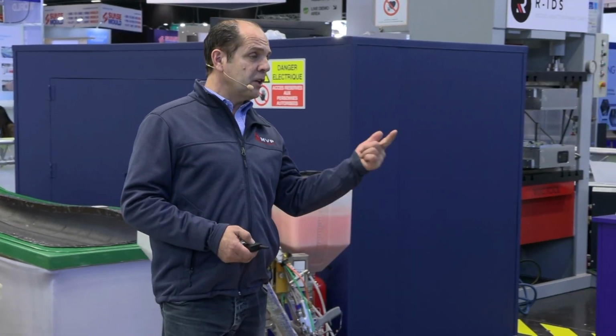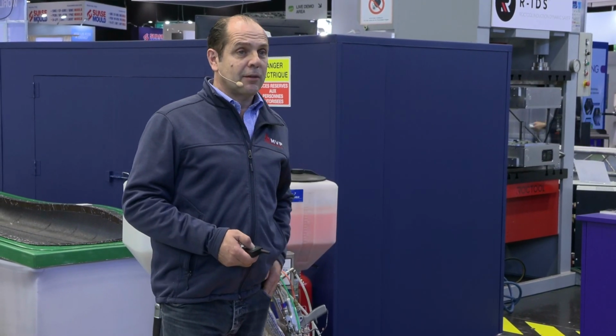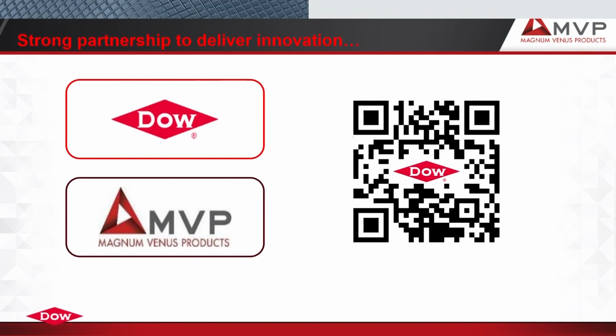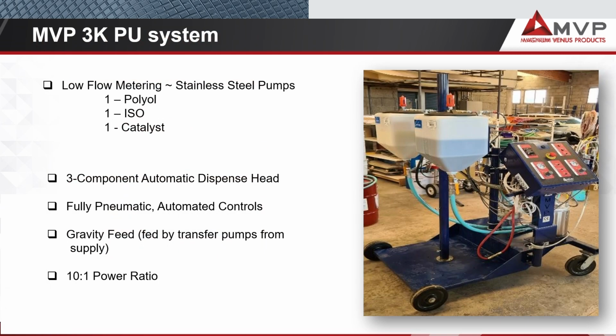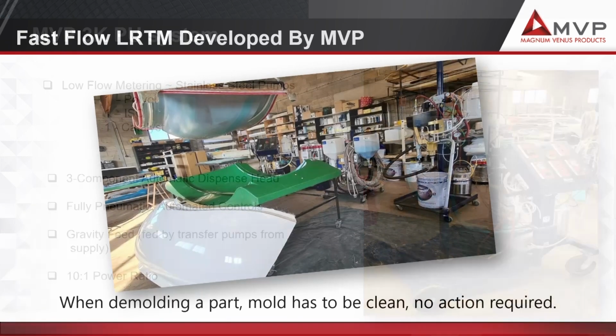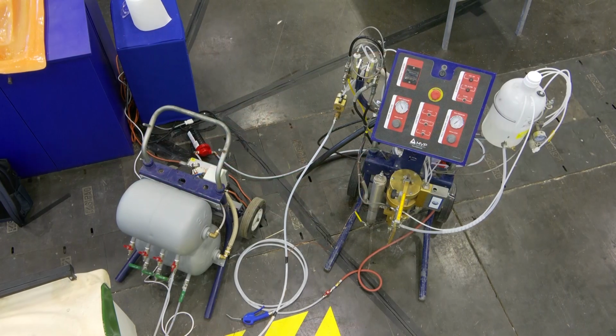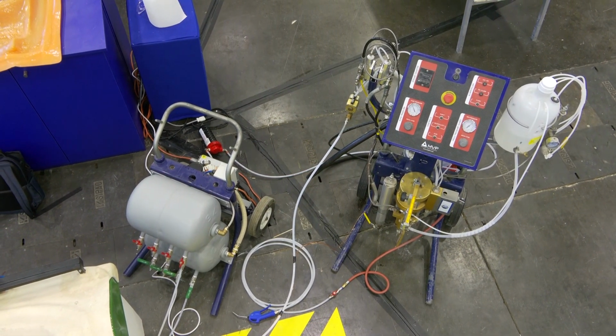So it's a 3 component system. You have the polyol, the ISO, and a catalyst, which is a special catalyst for PU. That's developed by Dow, and we have developed the process to be able to use that resin, because this resin has 2 main points, which are 600 centipoise and a 5-minute gel time. So it doesn't matter the size of the part, it has to be injected in less than 5 minutes. So for that, we have developed a machine, which is a 3-component machine, and the process to be able to inject the part in less than 5 minutes.